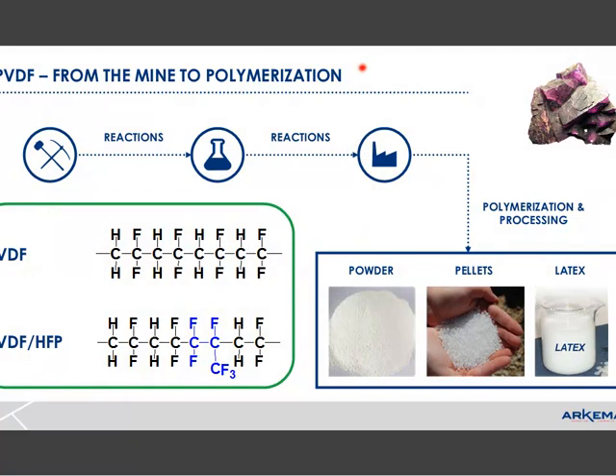Making a PVDF resin, it starts with a mineral called fluorspar. The fluorspar is where the fluorine comes from. The fluorspar is reacted to produce HF. The HF is used to produce fluorinated monomers, and those monomers are reacted to produce fluoropolymers. For PVDF resins, they tend to come in 3 forms. They can come in a powder, a pellet, or a latex.